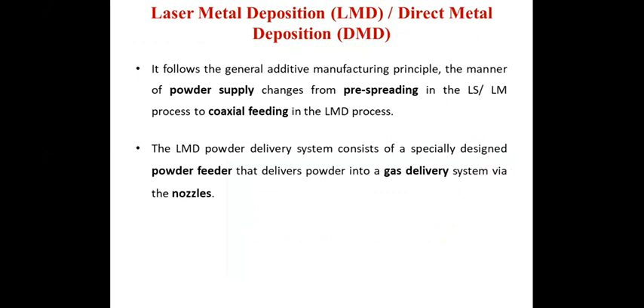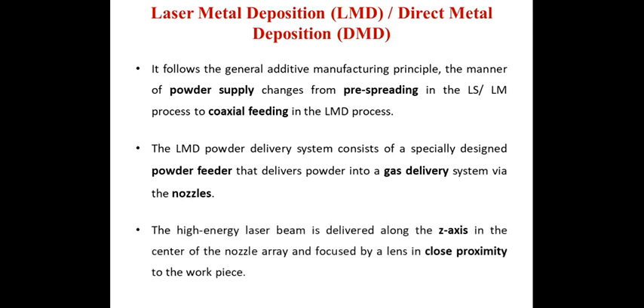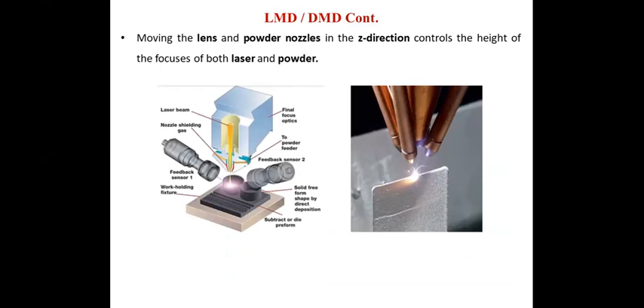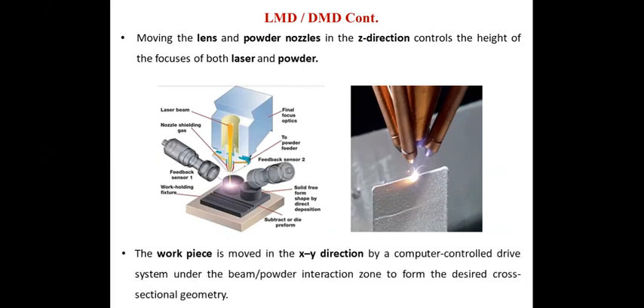The laser metal deposition powder delivery system consists of a specially designed powder feeder that delivers powder into a gas delivery system via the nozzles. The high energy laser beam is delivered along the z-axis in the center of the nozzle array and focused by a lens in close proximity to the workpiece. Moving the lens and powder nozzle in the Z direction controls the height of the focus of both laser and powder. And the workpiece, the part, is moved in the XY direction by a computer controlled drive system under the beam powder interaction zone to form the desired cross-sectional geometry.